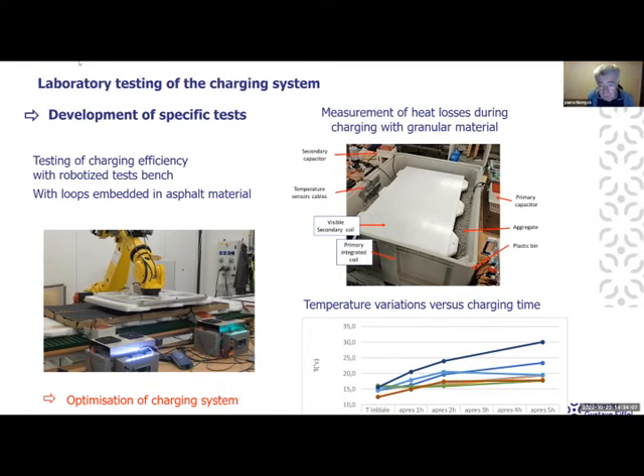And then we had this problem of heat losses during the charging. To evaluate the heat losses, we did also some tests of performance of the coils, but we didn't do it with asphalt materials. We did it with a granular material because Vedecom wanted to be able to install and remove the coil several times and to change the parameters of the test. So we decided to use a granular material which has no cohesion, because it was easy to embed and compact the material after placing the coil and then removing the coil again.